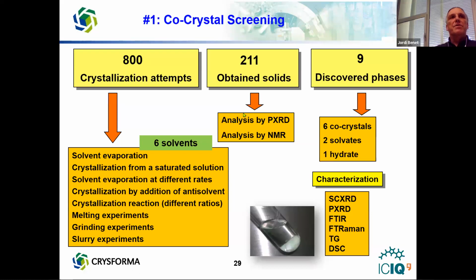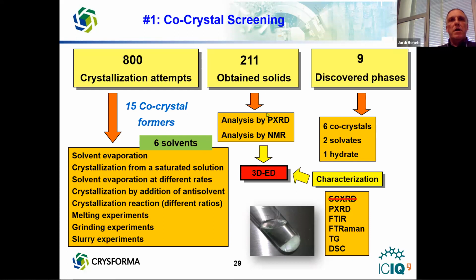This is an example of this process. We took an active pharmaceutical ingredient, wanted to make a co-crystal of it, and did around 800 crystallizations using all these methods and 6 different solvents. We obtained 211 solids, which were characterized by powder diffraction and NMR. From this, we discovered 9 different solid phases: 6 were co-crystals, 2 were solvates, and 1 was a hydrate. We would normally characterize them by single crystal, powder, Raman, infrared, thermogravimetric analysis and DSC, so TGA and DSC. But now we can introduce a new step.